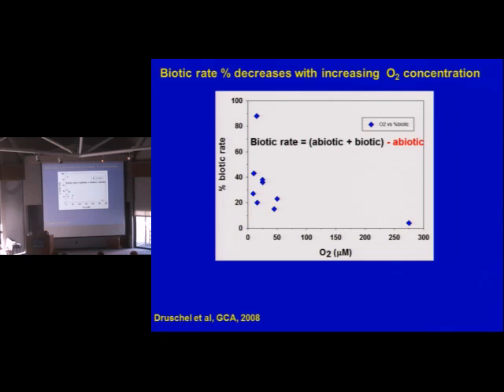So here's his percent biotic rate versus oxygen concentration. I wish he had done a couple more. We're going to fill in some things with different organisms. But the take-home message for this organism was that at about below 50 micromolar, we could definitely see that there was a decent biotic rate. Once you got above that, with the one data point, it was tougher. We've done a couple other experiments to show that, but we're going to try to fill it out with about 2 or 3 different organisms, because we have found some organisms still doing well at 80 micromolar. Okay? One being Leptothrix, which Dave Emerson's been working with. So this gives you an idea that the organisms are able to compete with the abiotic rate once the oxygen level gets lower.